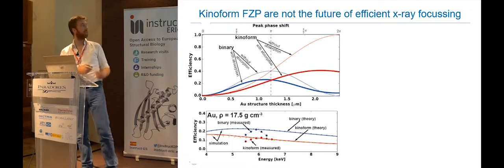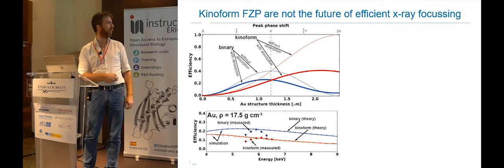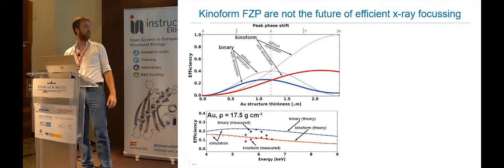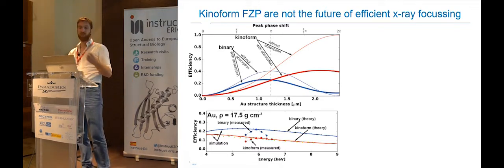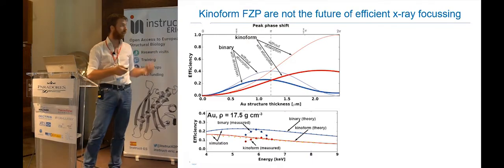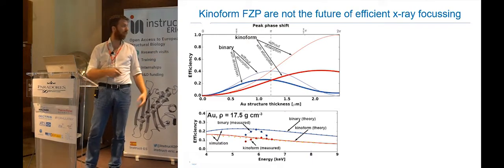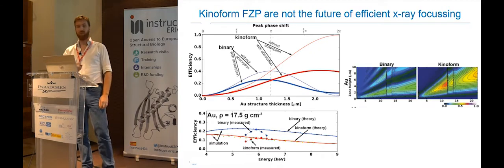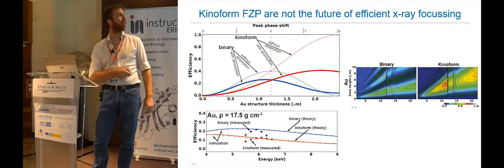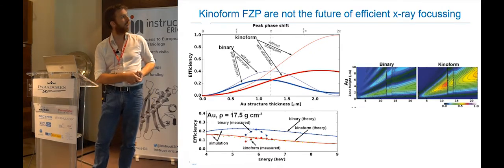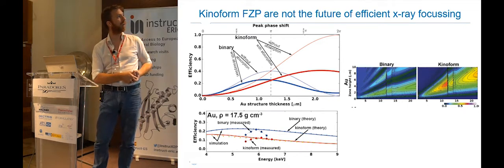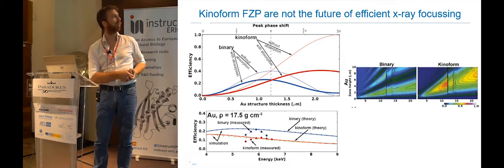So we did a lot of measurements, at 6 keV in this case, because that's where our detector was optimized, and we could get the theory and the measurement to match. So we ran more and more simulations, and we figured out that in theory you could get to 70%, but only for absolutely impractical heights, for example a 4 micron height.